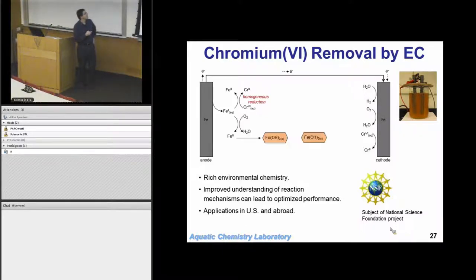Well, if we aerate the system, some of that iron 2 reacts with oxygen, which gives us rust. So now we have these little rust particles, iron hydroxide rust particles. Is that a good thing or a bad thing? I took away my reactant that was helping remove the chromium 6. That might be bad, but now I have solids, and solids are good if I'm trying to remove something that can stick to solids. Well, it can be good because the chromium 6 can actually get reduced on that rust particle faster than it can get reduced by the dissolved iron. So if I have a little bit of dissolved iron too and I have a particle, that reduction reaction is faster.